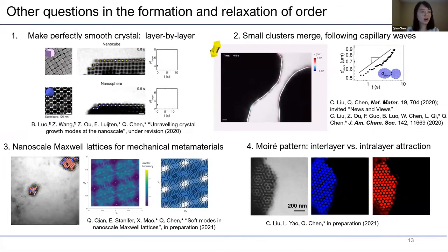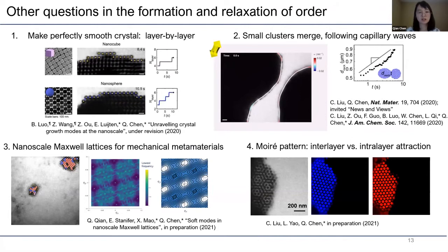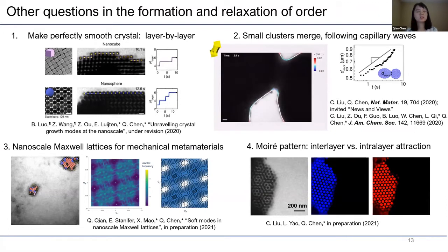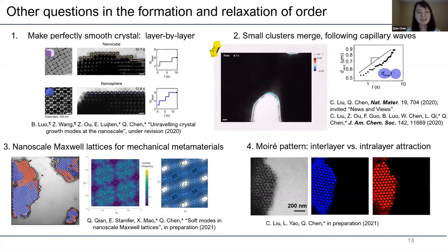And of course, we can extend to other questions related to the formation and relaxation of order now that we have the technique. In another collaboration with Eric, we noticed this universal layer by layer growth mode, which can be a beautiful strategy to make perfectly smooth crystals out of nanoparticles. Sometimes small clusters composed of nanoparticles can merge to grow bigger, with the interfacial fluctuation following capillary waves. And sometimes, depending on the symmetry of the lattices, they can fall into Maxwell lattices. They can have soft modes to allow for spontaneous reconfiguration, and such lattices can serve as good candidates for mechanical metamaterials.